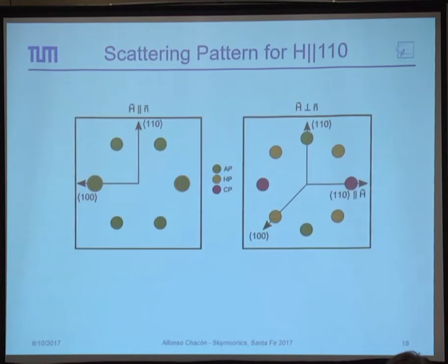So typically what we would expect to see are these scattering patterns. Here, the green dots belong to the skyrmion lattice. If it was a single phase state, we know that we have two phases, but just for the sake of cleanliness, we left those out. What is important here is that the helical propagation in this plane overlaps with those two spots belonging to the skyrmion lattice.